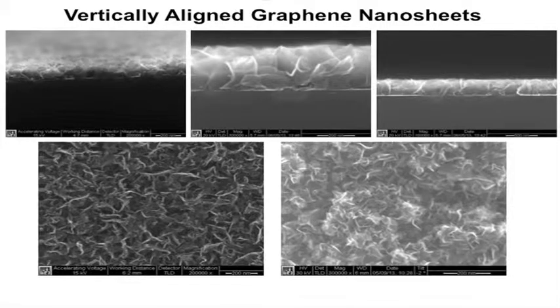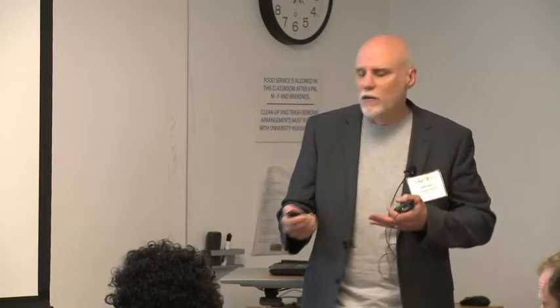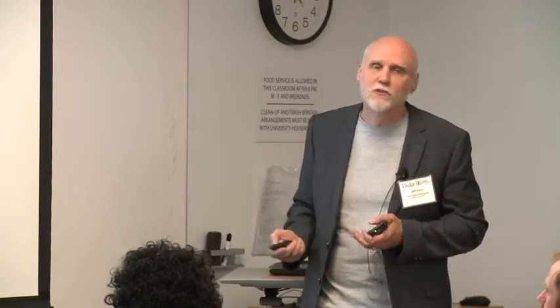We also grow graphene, and these are graphene flakes. So graphene is just a single sheet of carbon, and these have very specific properties that allow us to do energy conversion and storage more effectively than other materials. So we utilize these structures combined with the carbon nanotubes that I'll show in a minute to get the special properties of energy conversion and storage. Here is a MEMS fabrication, where if you look at this micron marker, these are really tiny panels that we flip up to be lateral devices on materials that allow us to make materials in a very small scale, as opposed to what you would traditionally see in material.